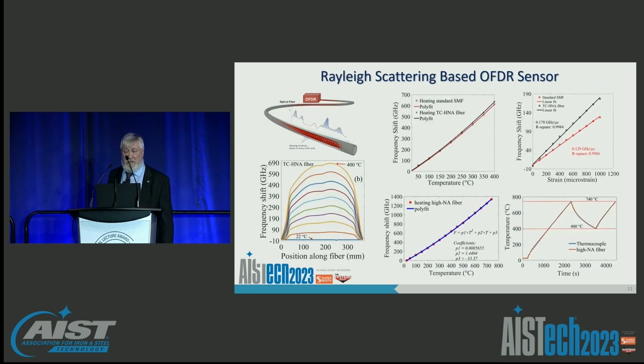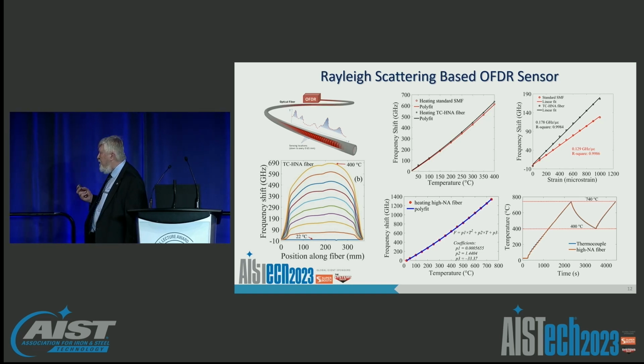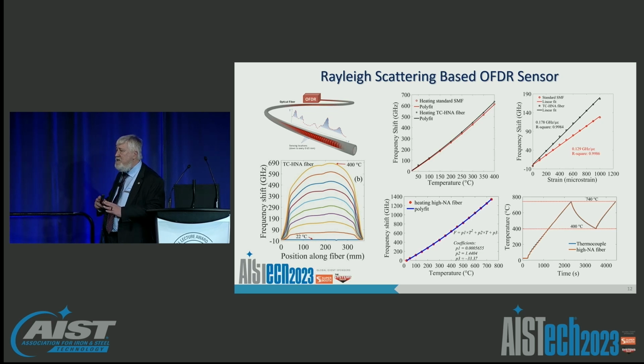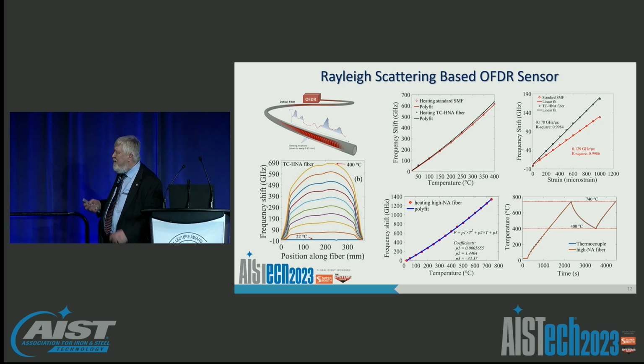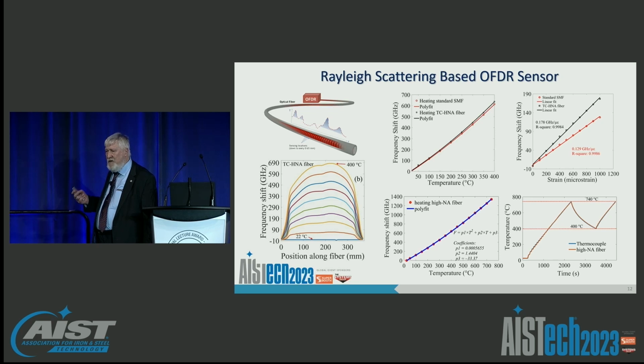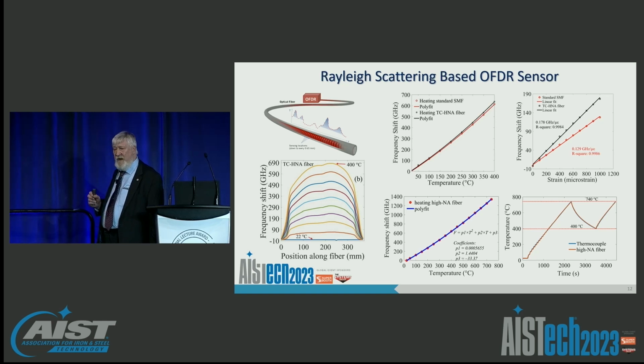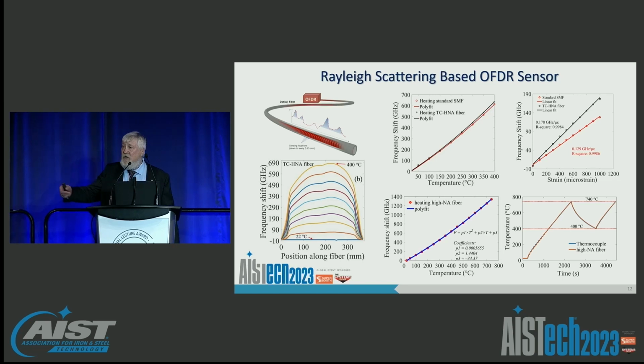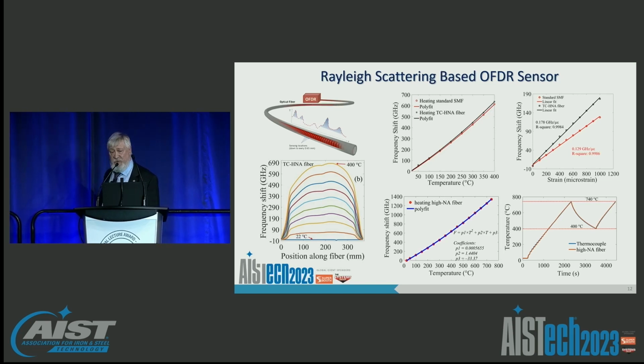So if I show you some of these measurement systems, you'll notice here that we actually have a system that can be calibrated both to temperature and to strain. And one of the challenges in these types of fibers is actually distinguishing what you're actually measuring, temperature or strain. And it turns out there are some really interesting ways to do that. You can either isolate the fiber from strain and measure temperature, or fully connect the fiber and measure a combination of temperature and strain. But we can also use different fiber numerical apertures in the same configuration and deconvolute the temperature and strain signals directly by actually comparing signals of two different fibers with different numerical apertures. And so a 2-fiber run can actually do a deconvoluted temperature and strain measurement, which is pretty exciting.